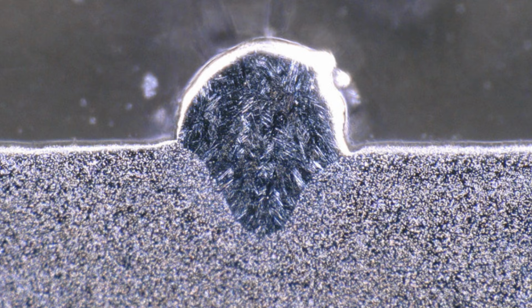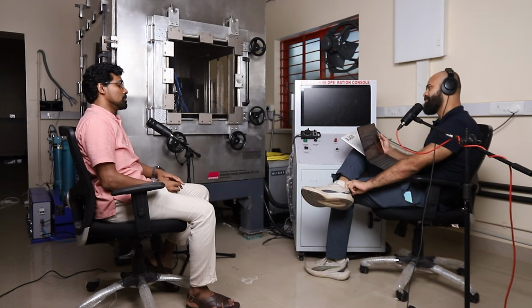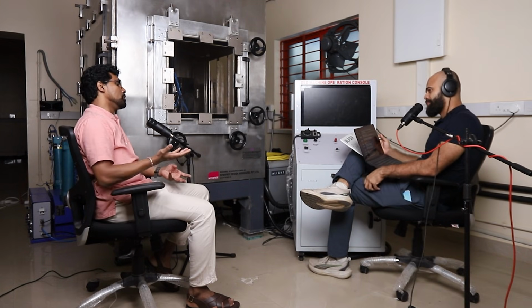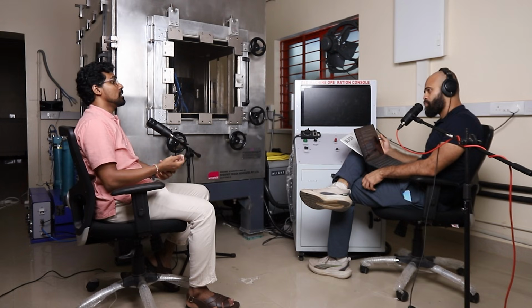And from there we try to understand how the solidification happens, and the things we try to extract out of our simulations are temperature gradients and the melt pool shapes. Melt pool shape is the liquid and solid interface. So it would form a liquid pool, and then as you scan the laser, that liquid pool will just move, and the trailing edge of it would solidify, and this liquid pool would keep moving. Now that's very interesting to see. So we try to understand what kind of melt pool shapes there are, and what the solidification velocity is.